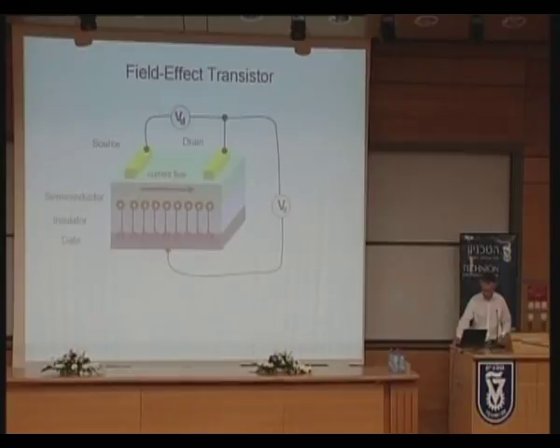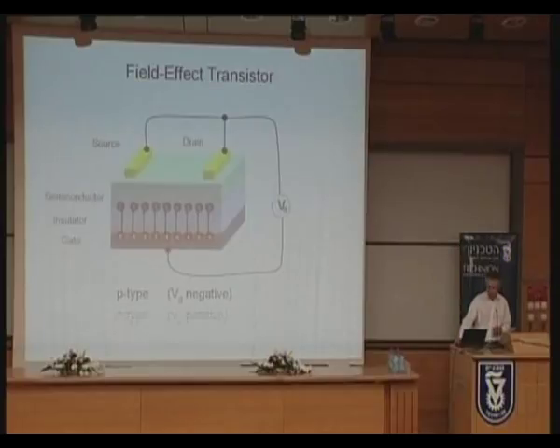So one final little trick is back to the structure of the field effect transistor, and you may have noticed that I chose to put a negative gate voltage on the device so we induce positive charges in the organic semiconductor. And in the literature, that's almost universal what is found. I mean, in principle, one would expect we could simply reverse the gate voltage and induce negative charges if we have a positive gate voltage. The problem is that in general they don't work.